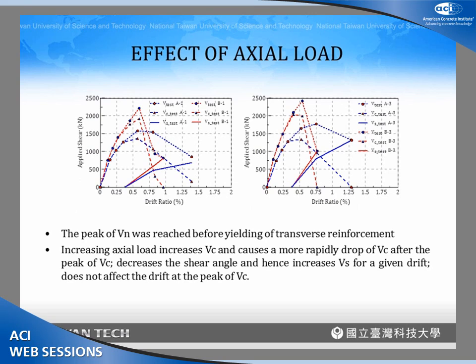So this plot shows you the relationship between the total applied shear strength, the shear strength from the concrete, and the shear strength from the reinforcement versus the drift. So you can observe that the peak of the concrete shear strength was reached before the yielding of the transverse reinforcement. This is different from what we know from a typical textbook. From a typical textbook, the assumption is that when you have yielding of the transverse reinforcement, then after that you get the peak shear strength from the concrete. But from our test result, we found that the peak concrete shear strength was reached before the yielding of the transverse reinforcement.